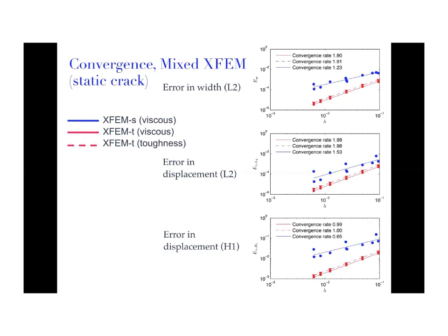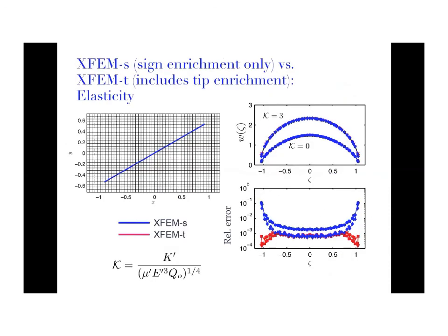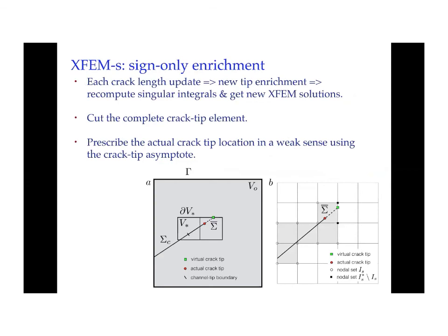Now, if you use the same sign enrichment for a non-planar fracture, when you start to curve your fracture, the curvature in the algorithm is based on the stress intensity factors, and stress intensity factors are linked, of course, to the singularity. Once you dispense with the singularity in the crack tip enrichment, you cannot get this correctly.